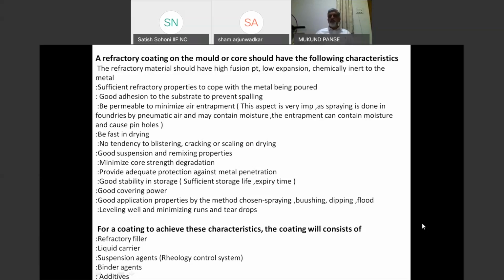The mixture should have good suspension. The core or mold strength should not degrade. The metal penetration should stop. For all these, the basic agents are, as discussed, refractory filler, liquid carrier, suspension agent, binding agent, and certain additional additives are required so that the spread of the metal or the scaling, cracking, blistering properties are adjusted.